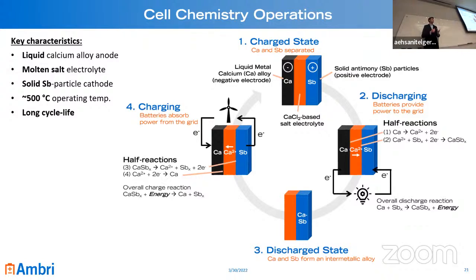Now, to charge the battery up, you simply pump electrons in the opposite direction. Electrons come back, causing the calcium to come out of the antimony into the salt and then replate and recreate that liquid electrode every time the battery is charged. So you're actually destroying and then recreating that negative electrode every time the battery operates. And that's one of the reasons the battery has very good cycle life, because you're destroying and recreating this electrode every time. So you don't have residual particles that can have film formation or particle cracking or other mechanisms that cause typical batteries to fade and fail.